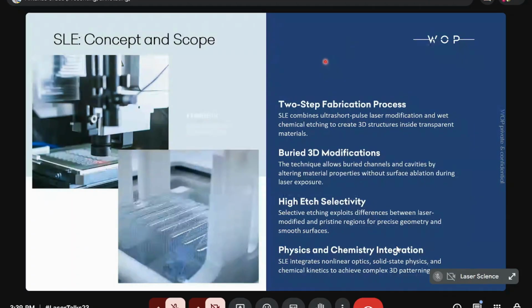Again, this is a two-step fabrication process. And what I have to mention is the selectivity of etching, meaning that the etching speed for laser-modified material and non-modified material should be as high as possible.